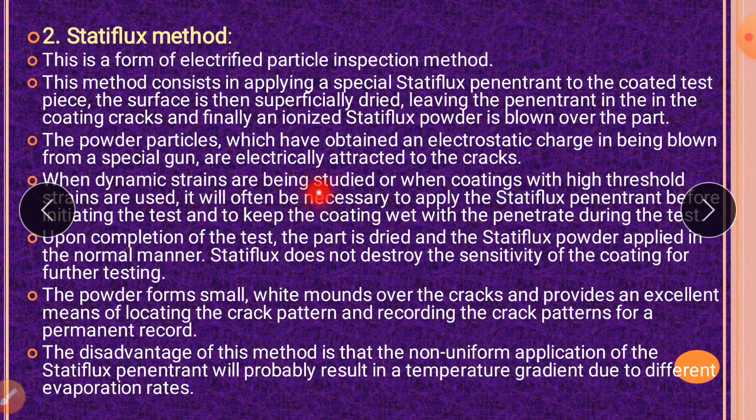When dynamic strains are being studied, or when a coating with a high threshold strain is used, it will often be necessary to apply the Statiflux penetrant before initiating the test and keep the coating wet with the penetrant during the test. Upon completion of the test, the part is dried and the Statiflux powder applied in the normal manner. The Statiflux does not destroy the sensitivity of the coating for further testing. The powder forms small white mounds over the cracks and provides an excellent means of locating crack patterns.